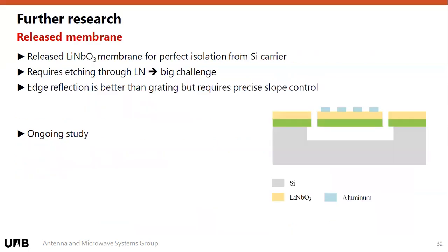Just as a further research topic, there's something that CNM has also been working on, which is that maybe we can also try our wafer with the released membrane approach, because then your Q goes way up. Although we have this simple λ/4 layer of silicon oxide isolating from the substrate, it is narrow band and provides a limited amount of reflectivity and a limited amount of confinement from the silicon substrate. If you put air there, you have perfect confinement, so all your energy gets trapped inside the plate.